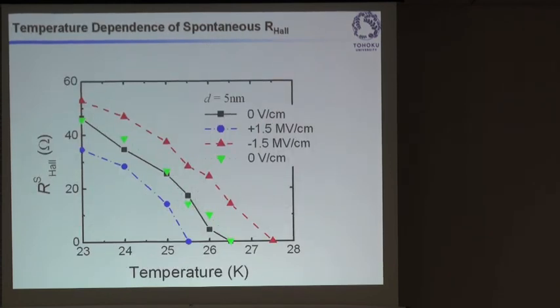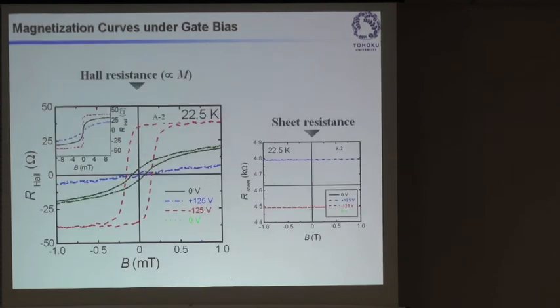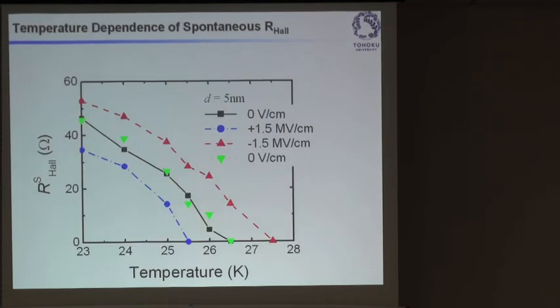You can also analyze the Hall data to determine the spontaneous magnetization, or the quantity that is proportional to spontaneous magnetization, measured by the Hall effect. So this is the temperature dependence of the spontaneous magnetization. And by definition, when the spontaneous magnetization becomes zero, that's your ferromagnetic transition temperature. So clearly, you can change the ferromagnetic transition temperature by 2 Kelvin, in this case, by applying an electric field. So in this temperature range, you can turn on and off the ferromagnetic phase.